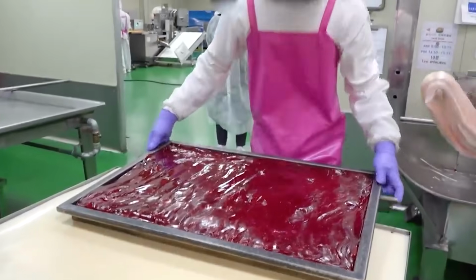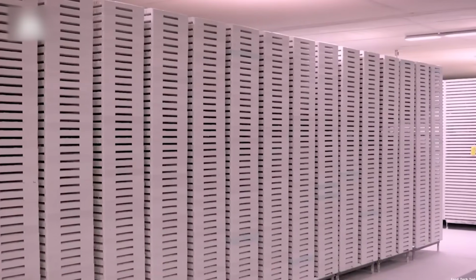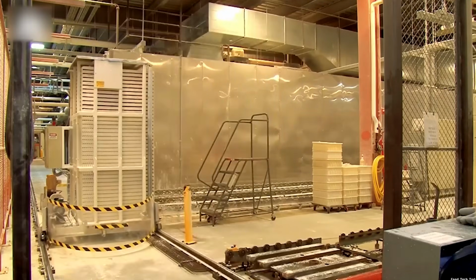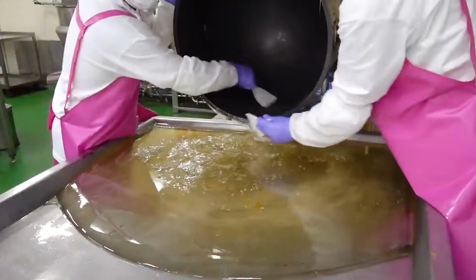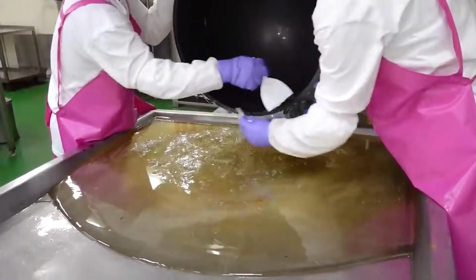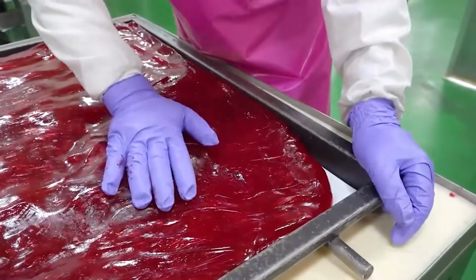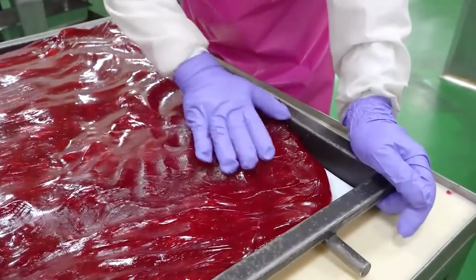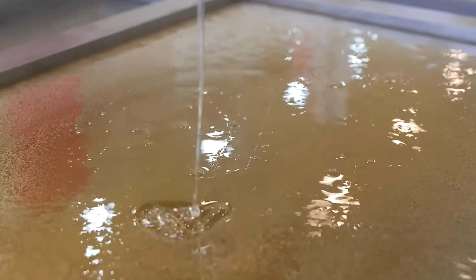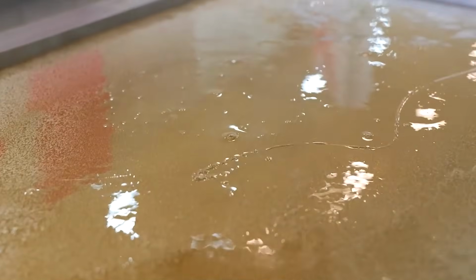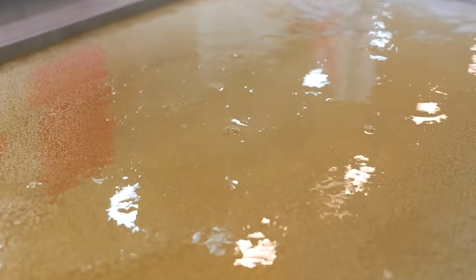Cooling begins immediately after casting. Cooling plates under the belt pull heat out evenly. Air above the sheet can be controlled to prevent moisture pickup and to manage surface set. The goal is to transition the syrup from a viscous liquid into an amorphous glass without large crystal growth. Large crystals would create a gritty texture and weaken control of fracture. Rapid controlled cooling helps keep the structure glassy.